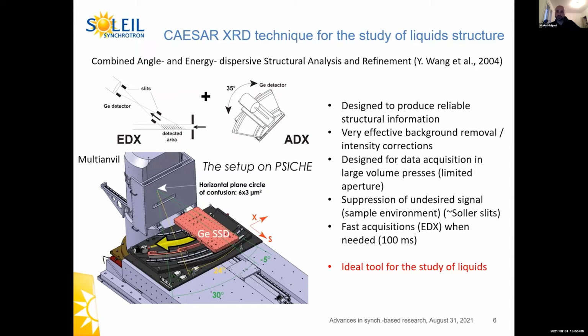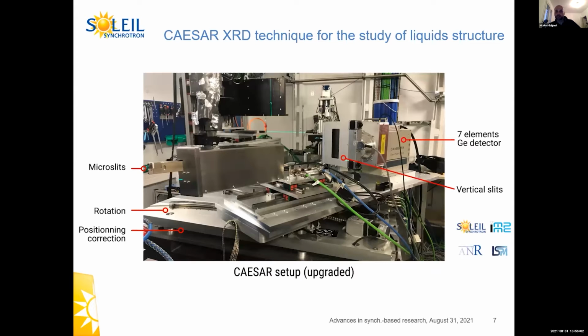And if we need, we can just fix the angle of the CAESAR system and then collect data at this fixed angle. This is the standard EDX system. And we can do very fast acquisition in this configuration, down to 100 milliseconds or even less. So that's the ideal tool for the study of liquids in large volume presses. This is a picture of the setup on the beamline with the slit system, with the micro slits, and the germanium detector we use. It's 7 elements that are behind the slits, and the rotation axis.